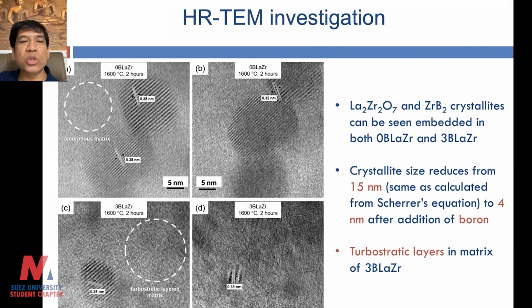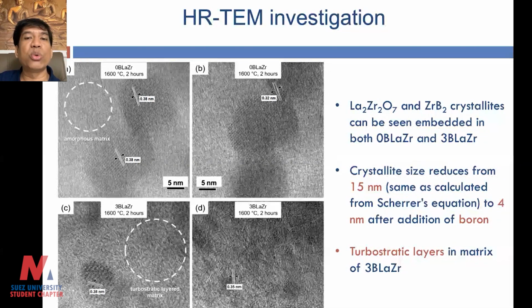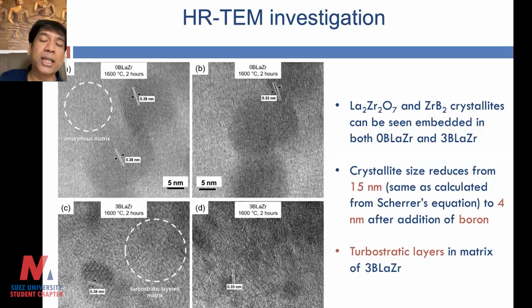And if you look at the high resolution transmission electron micrographs, just to give you an idea, you can see very fine nanocrystals of the phase that we want. So we can engineer what kind of crystals we want. For example, the micrographs indicate the presence of lanthanum zirconate and zirconium diboride. Both are very important for us. Zirconium diboride is very important to retain the high temperature stability. Lanthanum zirconate helps us to increase the oxidation resistance of these materials.